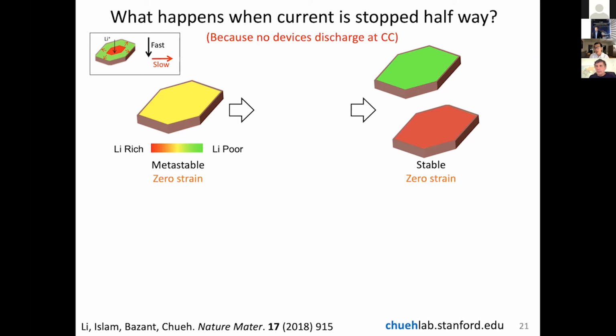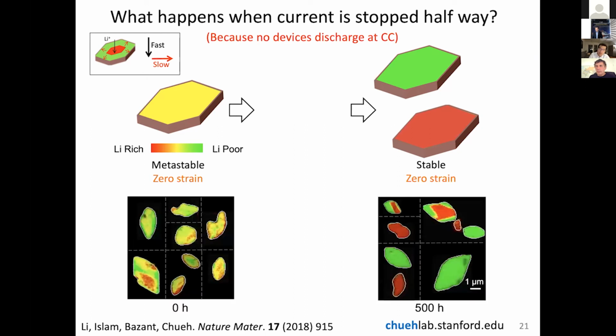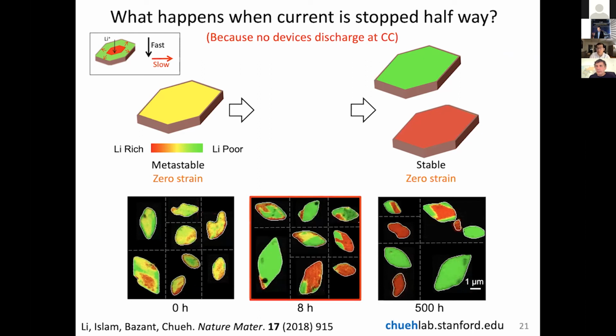So schematically on the right, I'm illustrating lithium poor particles and lithium rich particles. So ideally, this is what will happen because you avoid the cost of the interfacial penalty of forming the boundary. But it turns out that when we do the experiment, we don't see this stable configuration until a very long time, several hundred hours. And at any reasonable time frame, you actually see the intermediate behavior, which is forming the phase boundaries. So this is very strange to us because the classical picture of phase separation for a one-dimensional material like lithium iron phosphate is that in order to form the phase boundary, you have to move lithium across the particle. But lithium doesn't move in that direction. Lithium only moves up and down due to the anisotropic transport of lithium iron phosphate. So the lithium would have to come out of one channel and go into another channel. But if it has a pathway to do that, it will rather just partition the lithium into separate particles.